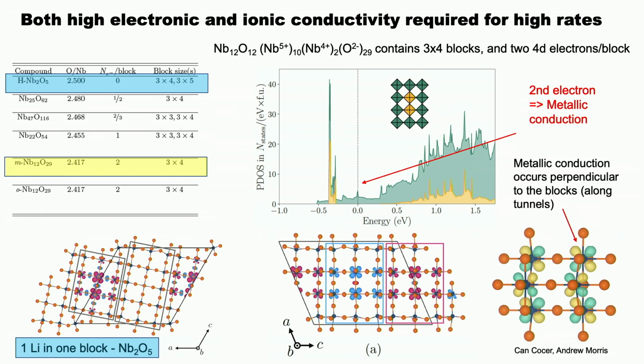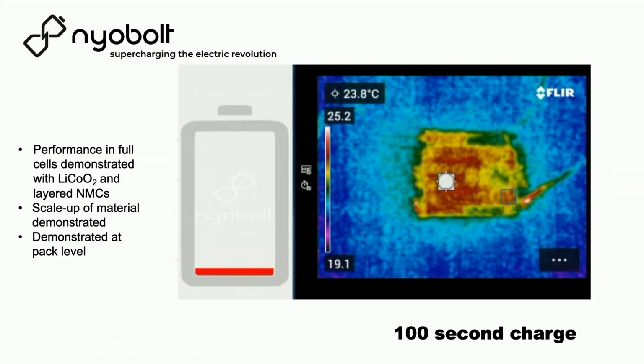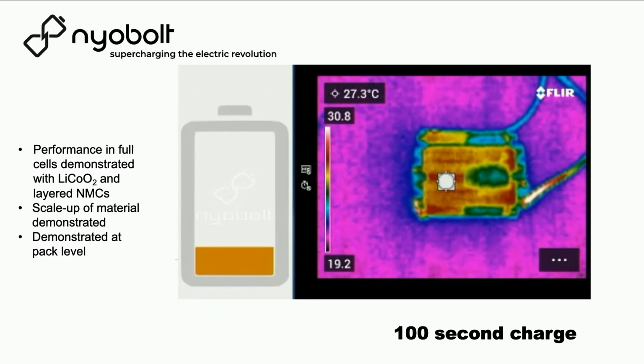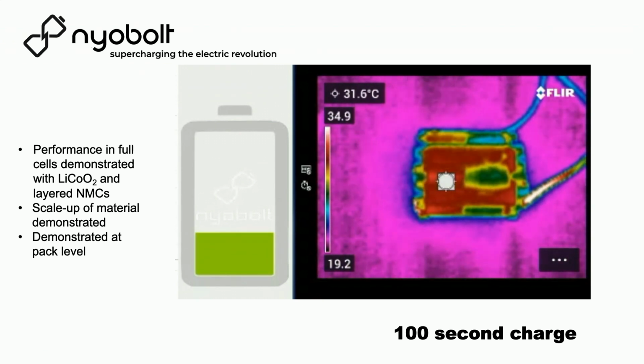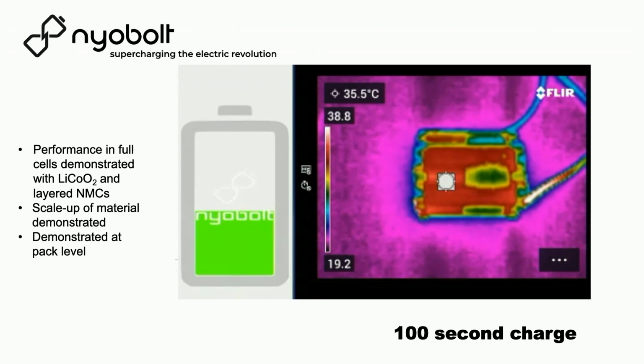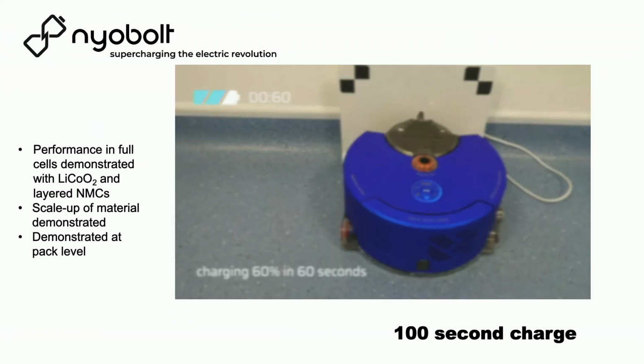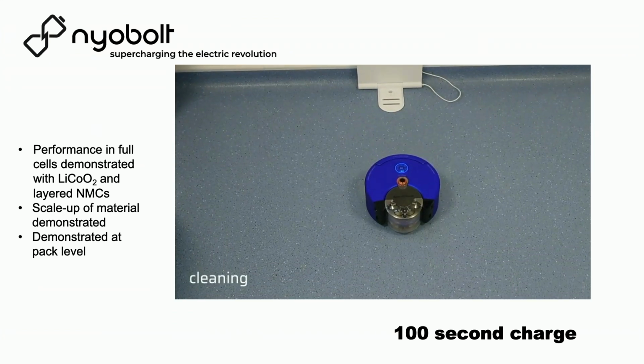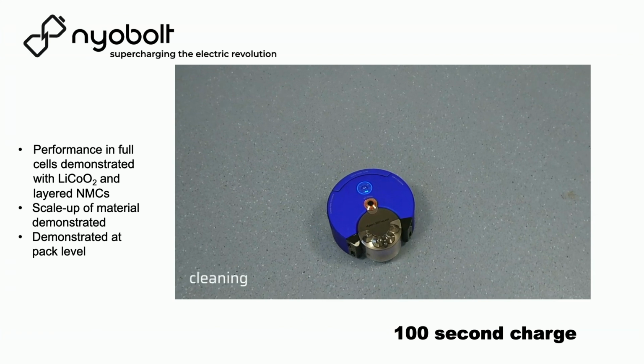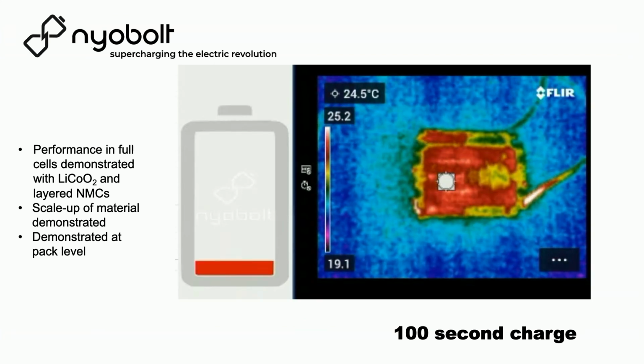And if you do DFT calculations, you end up with these, the first electron goes into these block orbitals where you have at low temperatures antiferromagnetic coupled electrons in one block and the other one, but the second one forms a band and it becomes metallic. And so then this is now the same picture of the Nyobolt, the same battery, and in 100 seconds you can see it only goes to 40 degrees, and then it's put into a Dyson vacuum cleaner. Before Dyson went off to Singapore. I wouldn't do this anymore.